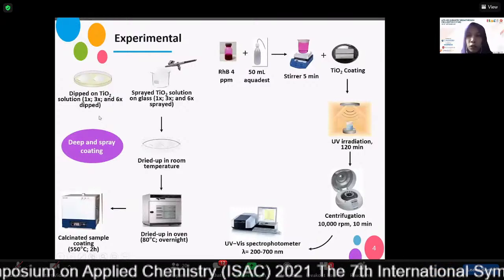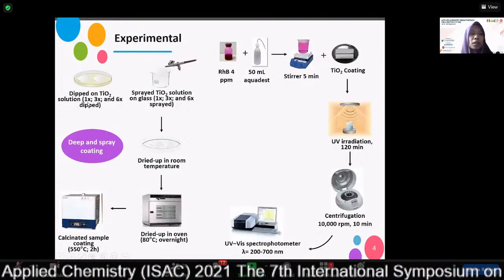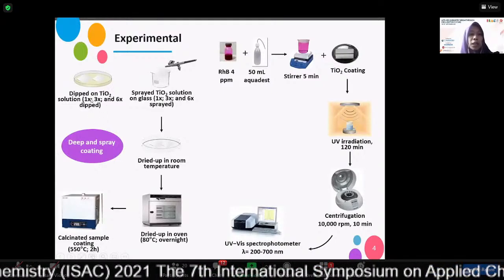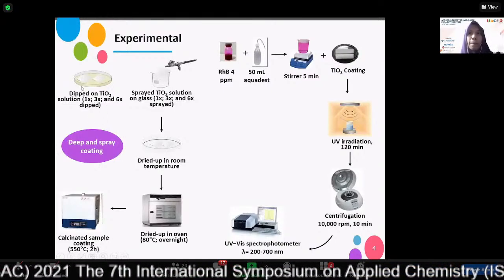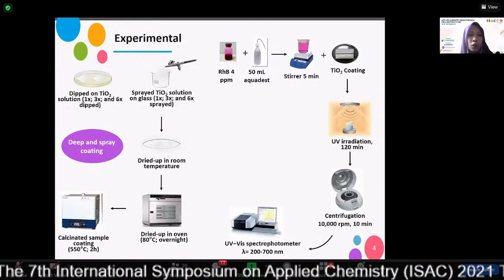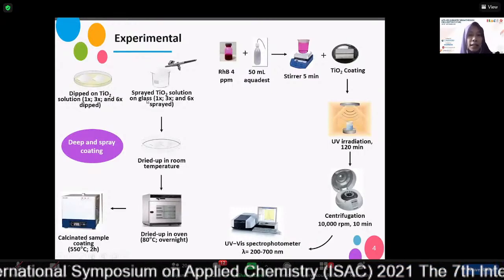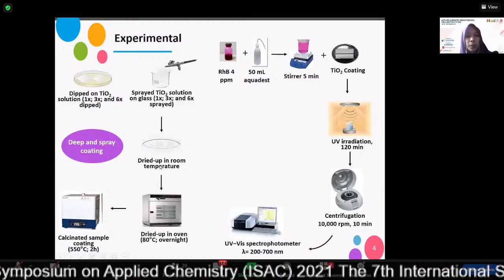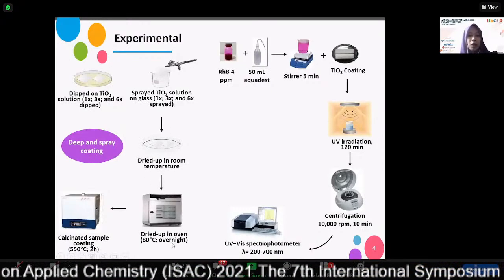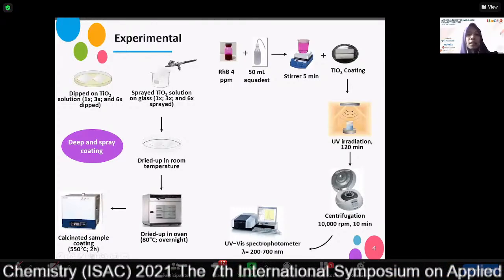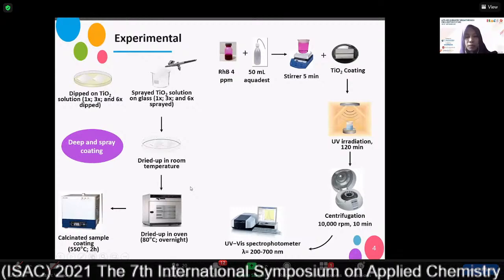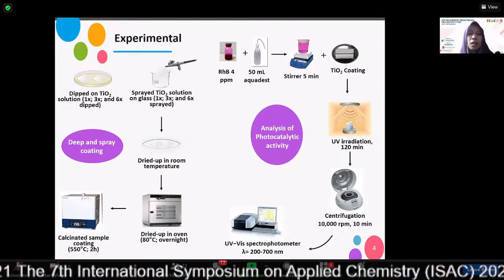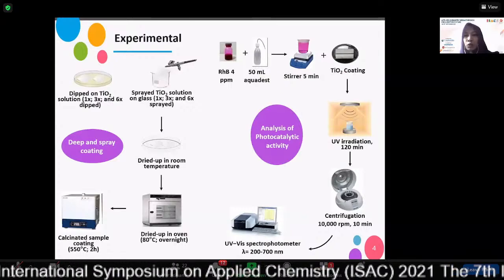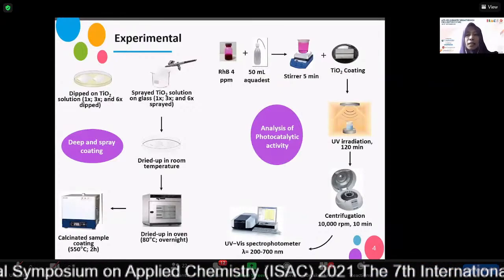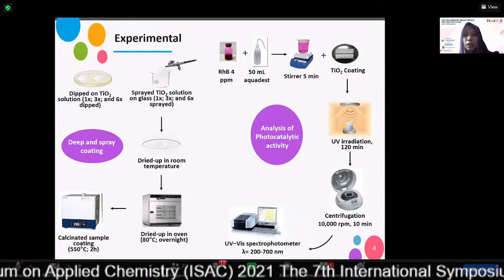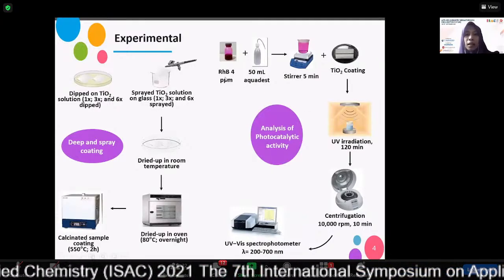After the solution was prepared, the glasses were dipped in the TiO2 sol, and the TiO2 solution was also sprayed on the glass. After that, it was dried at room temperature and then dried in an oven overnight and then calcinated for 2 hours.